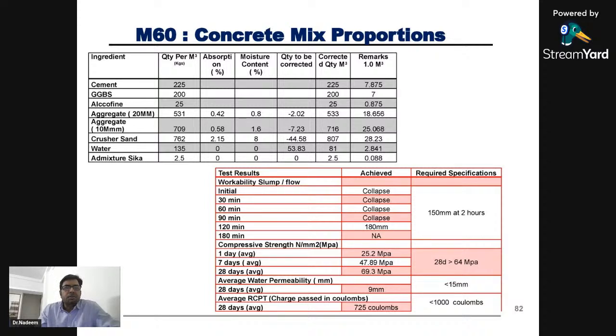You have to reduce the OPC content as much as possible. So only 225 kg, with 200 kg of GGBS, because all supplementary cementitious materials are found to be very good in achieving those durability parameters. If you compare, it is 50% cement and 50% SCM. Alcofine is 25 kg, a microfine material, and normal GGBS is 200 kg. And this is the mix design.